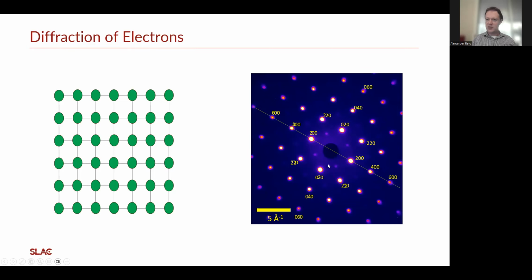And each of these peaks corresponds to a correlation length within the crystal. And in fact, what we're seeing here is essentially a reciprocal relationship. The real space lengths inside the crystal are being translated into momentum space separations of these peaks.